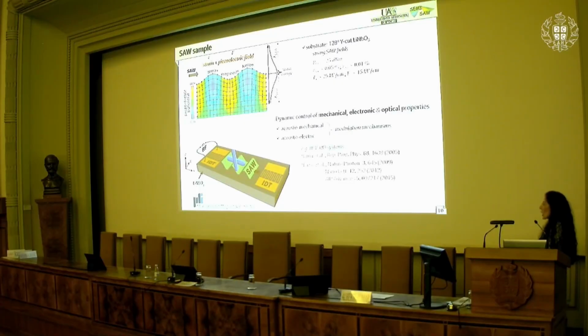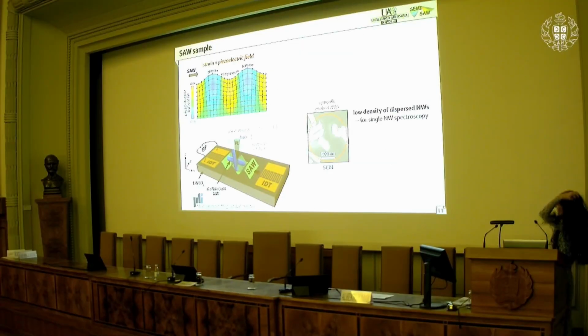Now, the use of such a highly piezoelectric substrate provides strong strain and piezoelectric field, which we can then use to dynamically, in real time, control the mechanical, electronic, and optical properties of whatever nanostructures we deposit on the surface of this acoustic delay line, as was previously shown in different semiconductor systems. So what we basically did is we mechanically removed the nanowires from their native substrate, and we dispersed them onto this acoustic propagation path in between the two IDTs. In this way, we obtained a low density of dispersed wires, so we could, in principle, perform single nanowire spectroscopy. We then analyzed their luminescence using direct optical illumination by a focused laser beam.